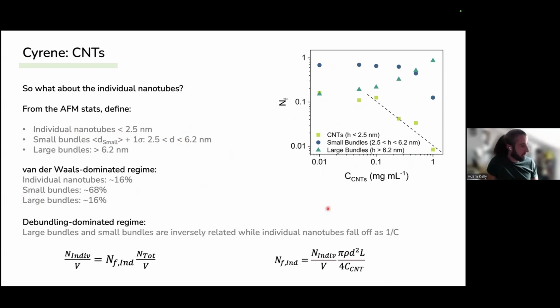If we move up above 0.1 mg per mL, we're in the debundling dominated regime. So this is where there's a relationship, an inverse relationship, I should say, between large and small bundles. And then the individual nanotubes fall off as 1 over C, which we can understand as taking the number fraction of individual nanotubes and multiplying that by the total number per volume. We fit that to the equation that we found on the last slide, and we get good agreement here, showing that the number fraction will fall off as the concentration increases.